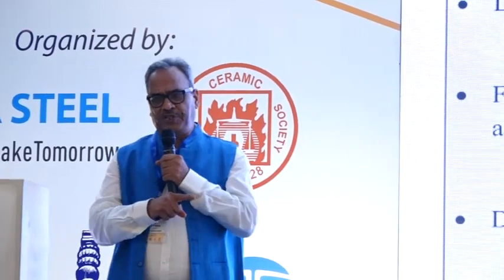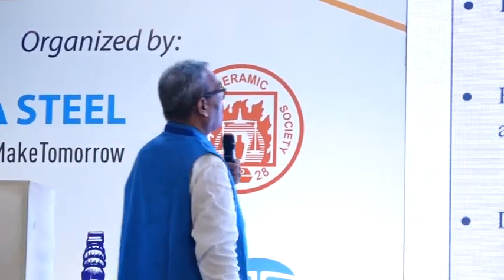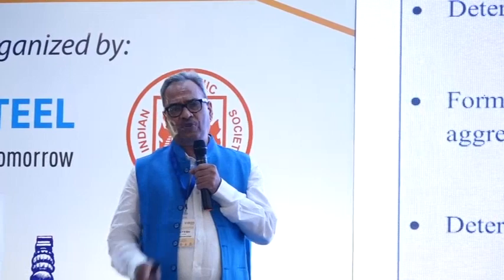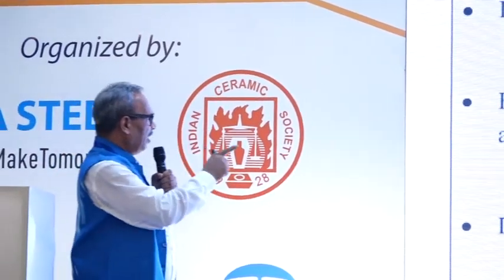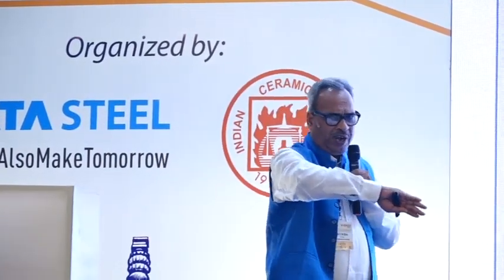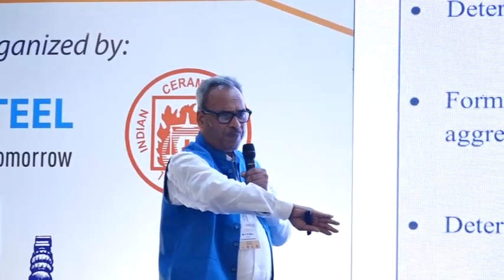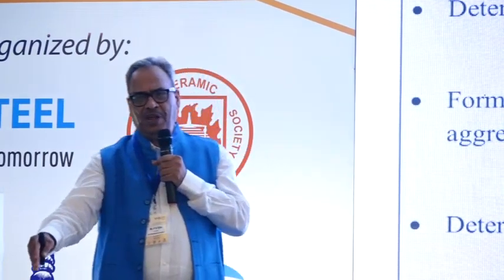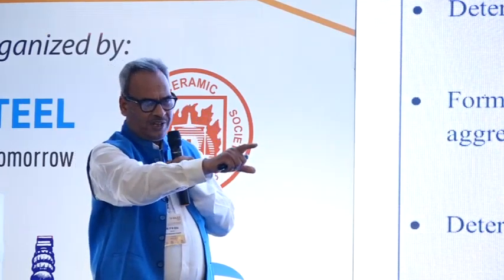So a broad objective of the follow-up study which is being taken up with JSW is determination of the maximum permissible free lime and magnesia content in the LD slag based fine aggregate. So what should be the maximum permissible limit? And how will it be decided? It will be decided by taking the corresponding free lime and magnesia, and correspondingly evaluating the expansion as a physical property. So chemical and mineralogical property and its correspondence in the physical property in terms of expansion. So the limit is set on both the chemistry and the performance which is physically observed.